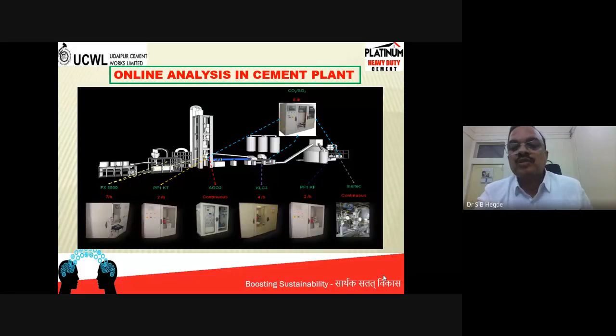the next box to this, the fifth box, is online particle size analyzer. So this is nothing but when we are producing cement, the particle size distribution is very important. As you must be aware, we generally maintain the residue on 45 micron. When we are talking about the fineness of cement, we are giving a target to the plant on 45 micron residue basis, 90 micron or 45 micron residue.